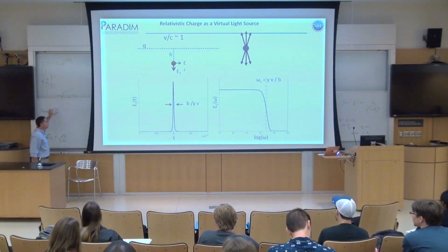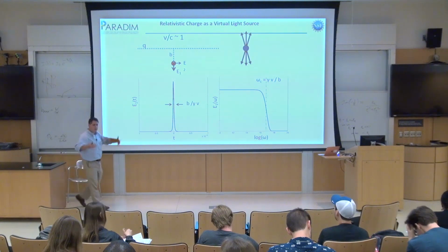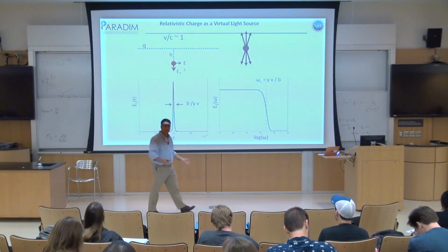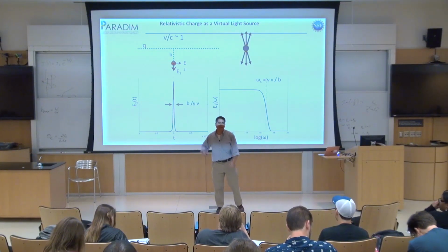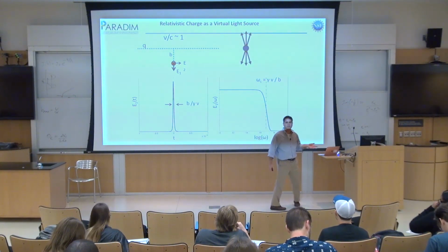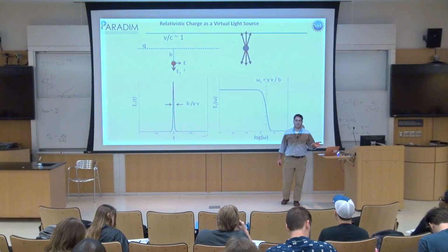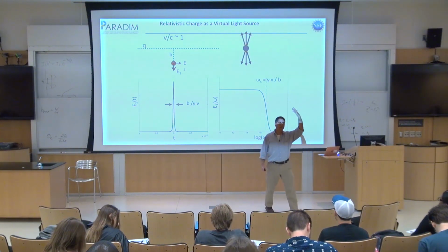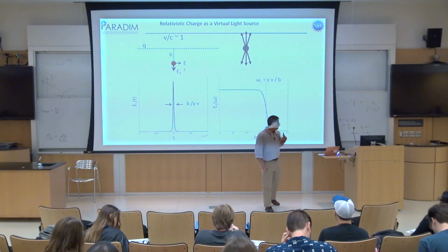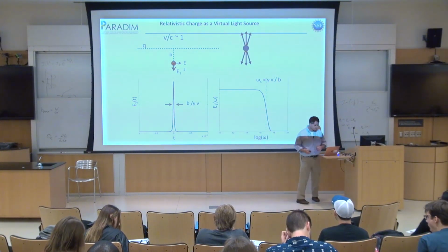That is a very simple rule of thumb. That's the length scale over which I get to feel an electric field from the atom. And that's the length scale over which I feel the naked, bare electric field of the system. For distances less than that, I'm going to have to solve Maxwell's equations to figure out the field distribution. For distances bigger than that, my electric field will decay evanescently, and life becomes much, much simpler.